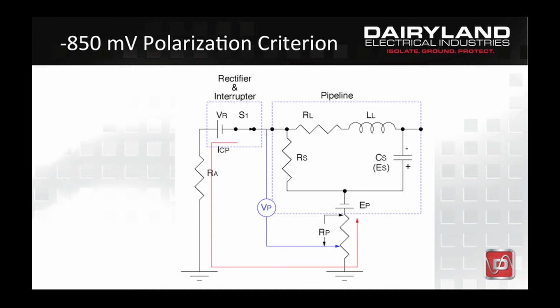When the voltage drop through the soil between the reference electrode and the pipe is included in the measurement, it makes the pipe appear to have a more electronegative potential and to appear better protected than it really is, because this voltage component does not contribute to cathodic protection of the pipe. To get at the true polarized potential, it is necessary to eliminate this I times R sub P voltage drop component from the measurement because it is an error term, commonly referred to as IR drop error.